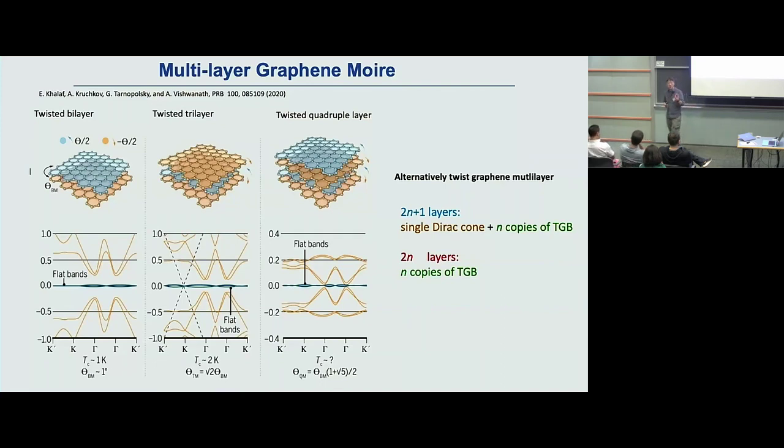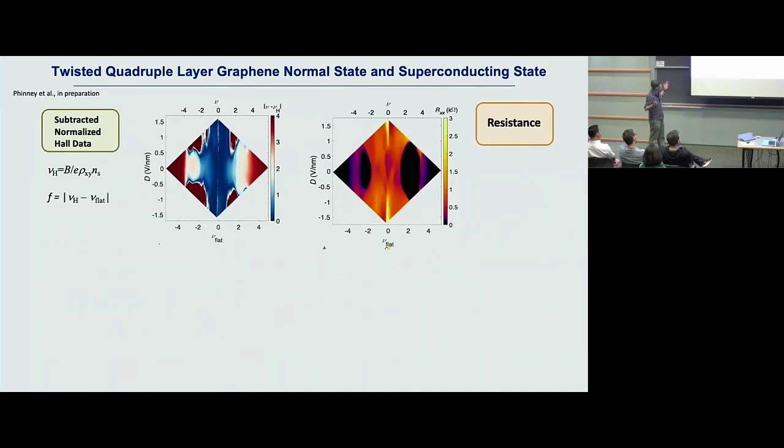Is superconductivity really related to broken symmetry states? Some recent work has claimed and shown this a little bit. Here, the recent development we show is 4-layer graphene with displacement field and filling. You can see the subtracted, normalized Hall coefficient, where you can roughly see the broken symmetry state numbers, the degeneracy number. And here the so-called nu equals 2 broken symmetry state appears, and it appears as the phase boundary of the broken symmetry state.